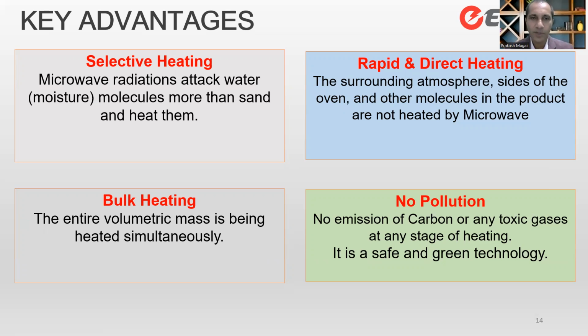And there is a phenomenon called bulk heating, meaning we are not heating only the surface. If you take oil fired, gas fired, diesel fired, any of these methods, electrical heating, infrared heating, in all the cases, the heat is generated outside and the heat is given to the core. So the surface will heat first, and because of conduction of heat, the heat will go inside. So the inner water will get the heat quite late, and you have to be very, very slow.